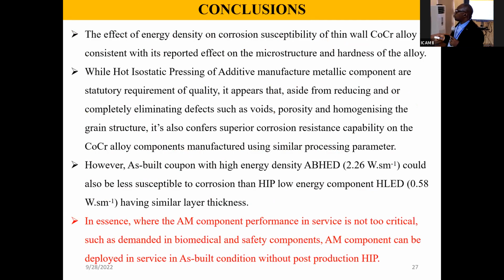So finally, what I found out generally is that while post-processing is a statutory requirement for quality, it also has a fair contribution to stability. And that the AM component can be applied in something where the requirement is not too critical, without post-production need, that is, without incurring higher costs. That's my conclusion. And this is consistent with key findings.